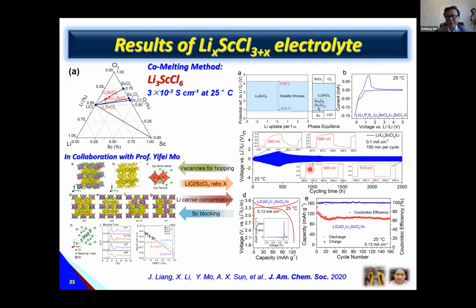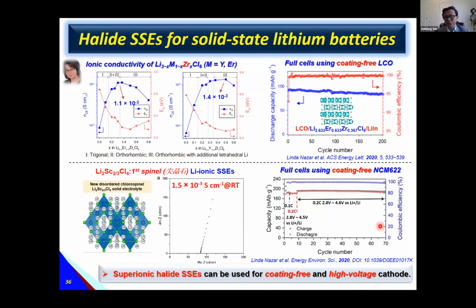We also demonstrate, for example, lithium to lithium is, in the beginning, forming an interphase and then later on is stable. So in this system, we didn't use an interlayer, directly using indium as an anode, we can run the battery. I'd like to mention that other groups also work on that. For example, Professor Linda Nazar's group works on that using zirconium doping in lithium yttrium chloride to increase ionic conductivity, and also works on lithium scandium chloride. They found that the spinel structure presents very high ionic conductivity up to 10 to the minus 3 as well.